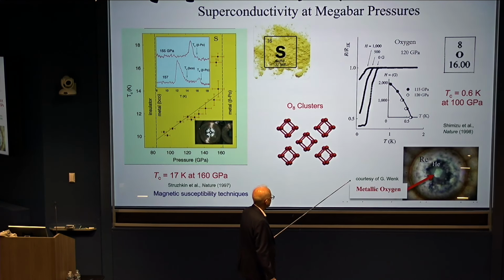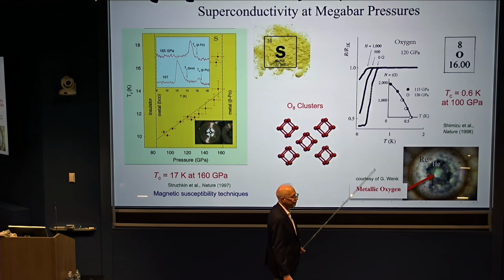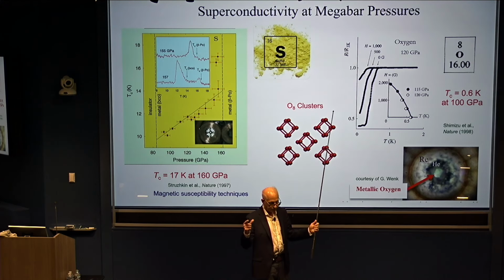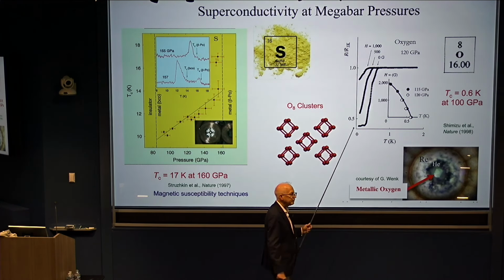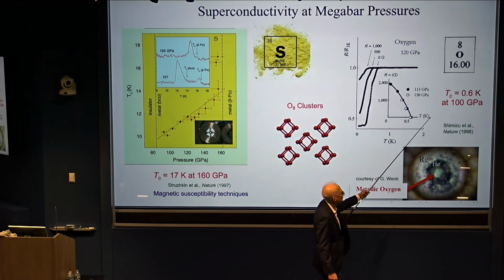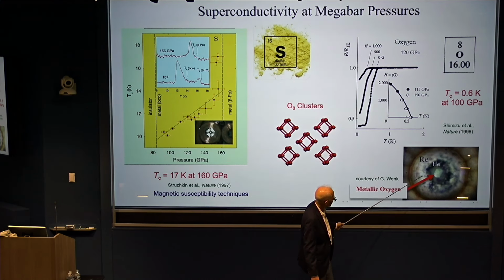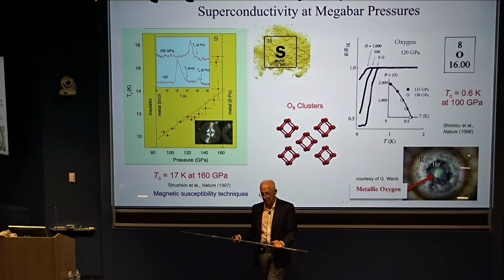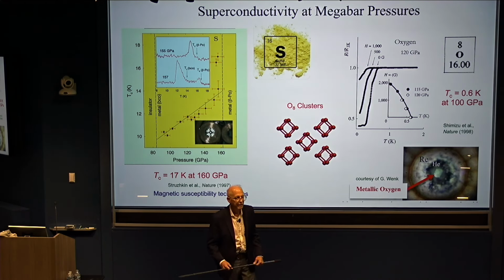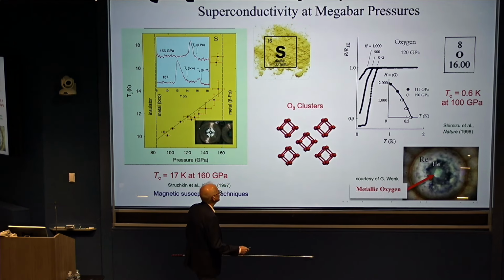About the same time, our colleagues in Japan were studying oxygen. So you think about 20% of the air, you separate the oxygen out, compress it, you can actually make it into a superconductor. A low TC, but a superconductor and a metal nonetheless. This is looking at a sample through a diamond anvil cell, seeing the metallic character of the oxygen. So this is pretty remarkable. These are remarkable transformations in other elements.